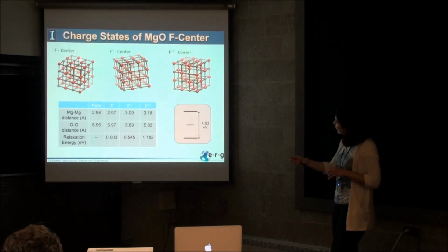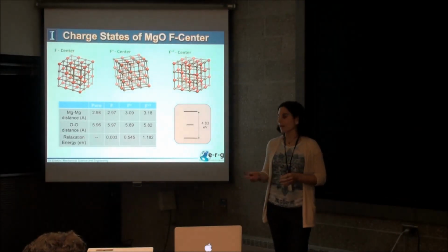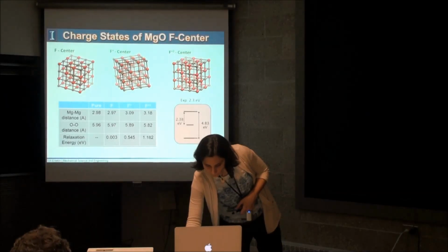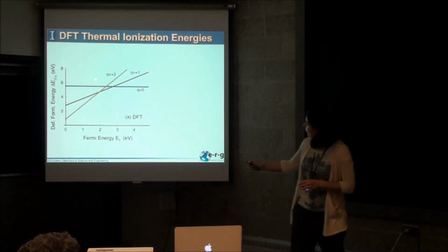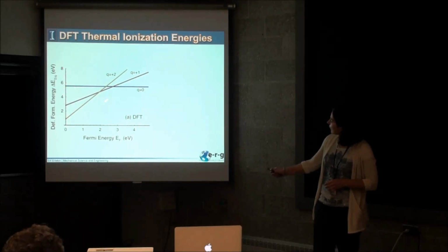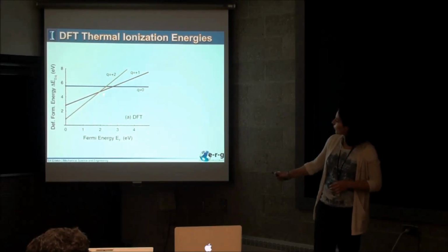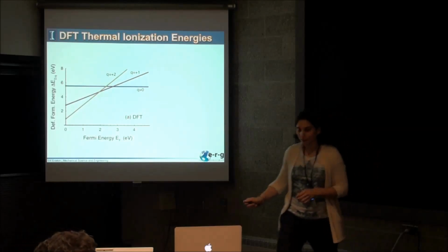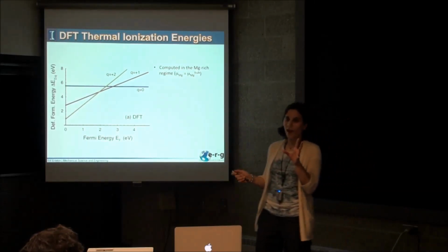And I decide to trust, for now, those DFT predicted configurations. Then using these DFT generated configurations and states as a starting guess, I use those in my QMC analysis to compute the energies of these different systems. Put those into quantum Monte Carlo. By computing the formation energies, I can compare defect formation energies in DFT for the neutral defect, the +1 ionized defect, or the +2 ionized defect. You can see where those thermal transition levels kick in according to DFT. But here's what I want to point out. This x-axis domain is going from 0 to about 4.8, the band gap of magnesium oxide according to DFT. That's where we know the problem is. In this particular case, this band gap is off by almost a factor of 2.